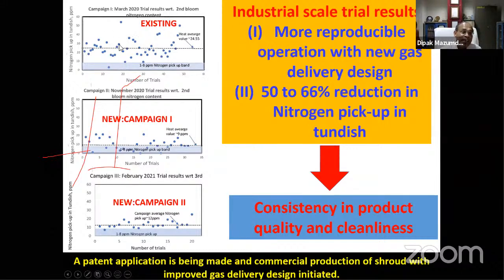So this is the existing. I have kept deliberately three figures. There is a campaign one figure. This is the ongoing campaign figure, and this is the existing shroud practices. Okay. And this is the nitrogen pickup in Tundish. I kept this axis deliberately the same. These are 60 ppm nitrogen. We have got about a maximum of 55 ppm. And you can look at the existing practice, where the average is about 25 ppm, and look at the scatter.